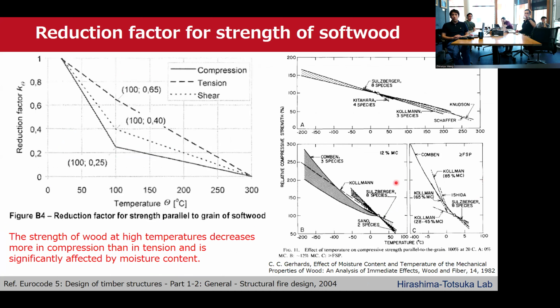Annex B of the Eurocode 5 advanced calculation method gives the reduction factor for strength parallel to the grain of softwood. The strength of wood at high temperatures decreases more in compression than in tension and is significantly affected by moisture content. This has been demonstrated through previous experimental studies, and these figures are examples of those reports.